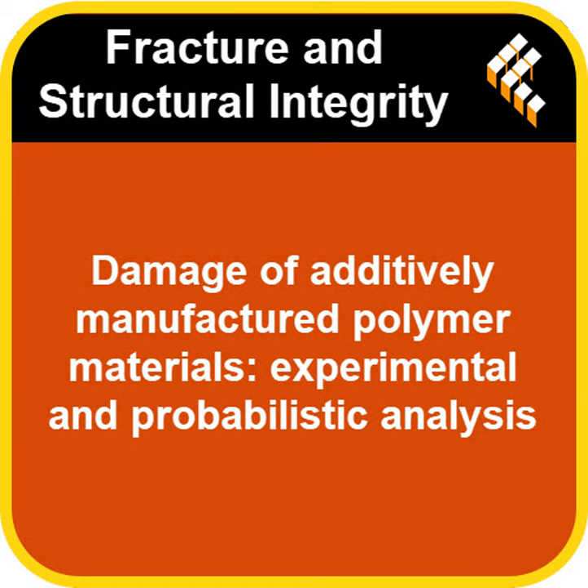That 50% mark is like a universal danger zone for cracks in this material under these conditions. It seems that way. They also use statistical methods, like Weibull analysis. Right, you mentioned statistics earlier. Yeah, to model the probability of failure or survival at different stress levels for these different orientations. It adds another layer, a statistical prediction layer, on top of the experimental observations. So beyond just observing how it fails, the next step is predicting when, statistically speaking. Exactly. Which leads to assessing the damage and ensuring safety. And the paper touched on different ways to assess and predict this damage. They mentioned methods like the unified theory and compared it, implicitly at least, to Miner's rule.